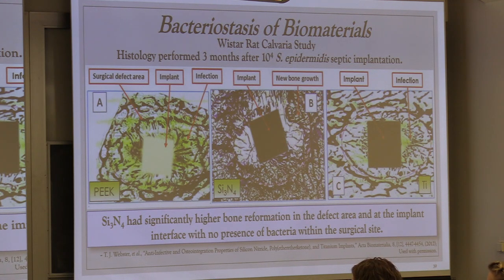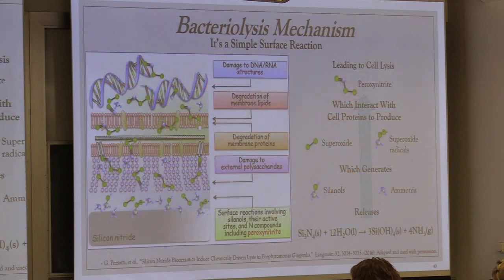So this was the first clue that we had that silicon nitride also exhibits this antibacterial capability. So there is a mechanism here as well. It's a very simple surface reaction. It's this equation down here at the bottom, which starts out that silicon nitride mixed with water elutes silicic acid and ammonia.